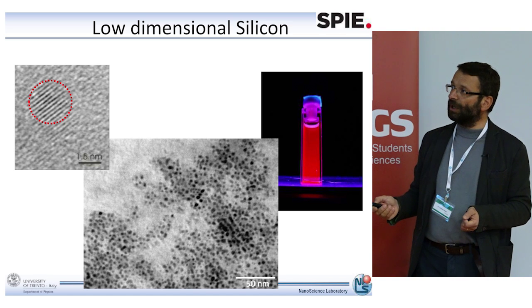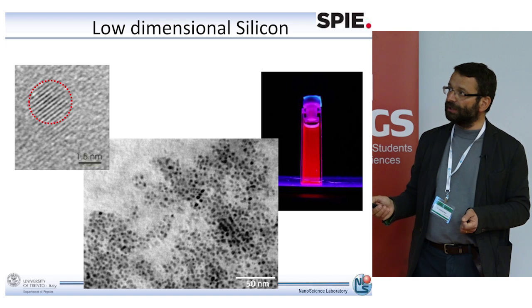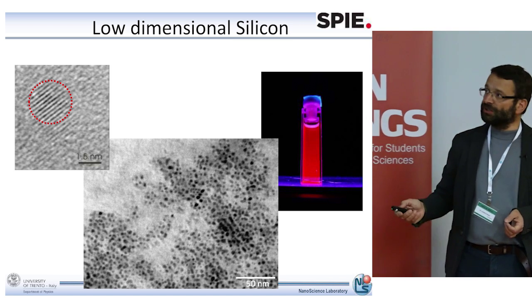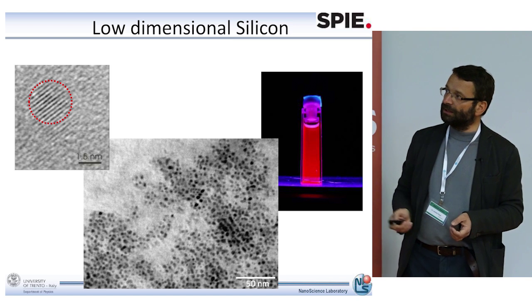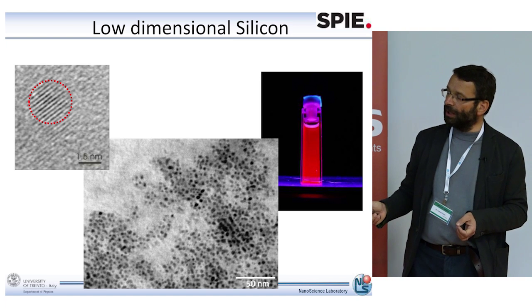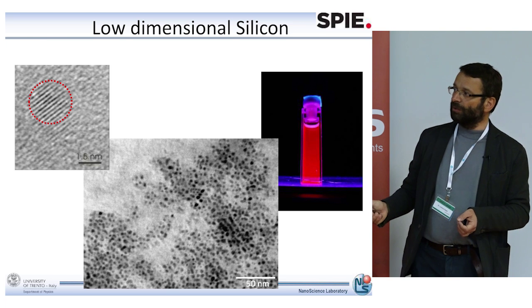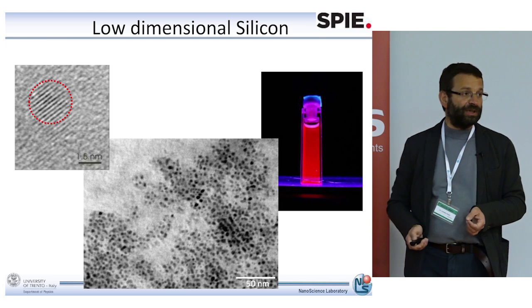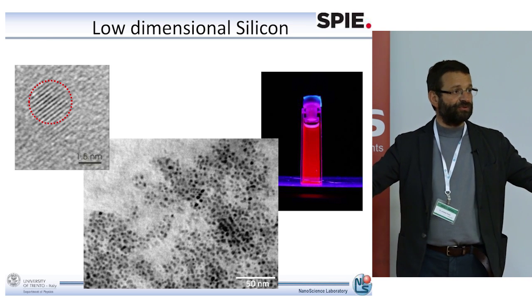So this is a piece of amorphous oxide, silicon oxide, where we have formed a silicon nanocrystal. So you see all the lattice planes here. This is a TEM image. So we do see all the lattice planes there. And this is a blow up of this. Here the length scale is 50 nanometers, so we can make many of those nanocrystals.